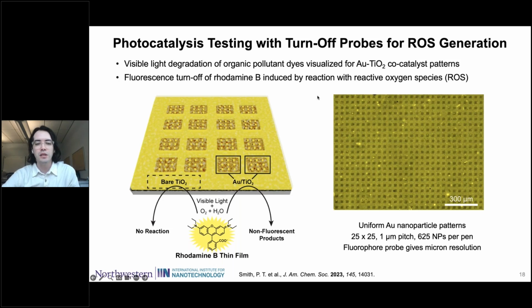And so to measure the extent of ROS generation within a megalibrary, we designed this experiment where we can pattern nanoparticles on a surface and then coat it with a thin film of this rhodamine B molecule. And so as ROS are being generated, the ROS will react with the rhodamine B, degrade it, and cause a loss in fluorescence. And so if we pattern these 25 by 25 micron squares of nanoparticles, and then do this experiment, we can see on the right this uniform loss of fluorescence induced by the gold nanoparticles generating ROS.